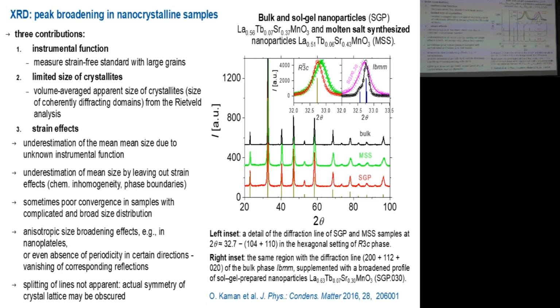All the time you should determine the instrumental broadening by measuring some well-crystalline, strain-free standard, for example, lanthanum hexaboride is often used, or some nice metal like wolfram can be used, tungsten. Then there is the second contribution to the line broadening, and that is the contribution given by scattering on domains of limited size. If the coherent diffraction occurs only on some nanoscale domains, there is this broadening, and we can analyze this broadening.